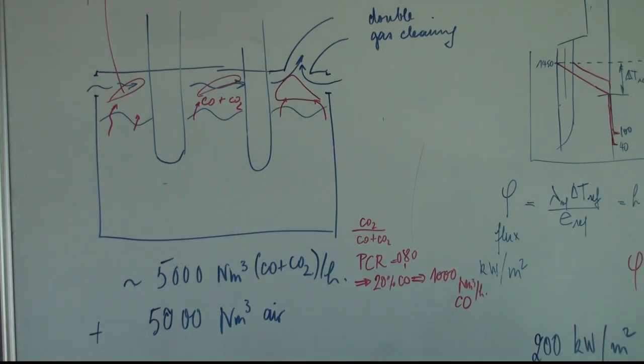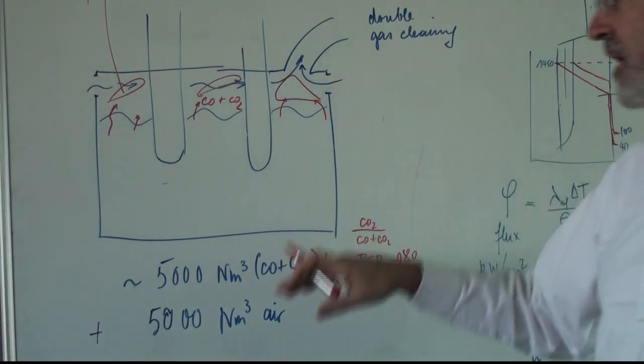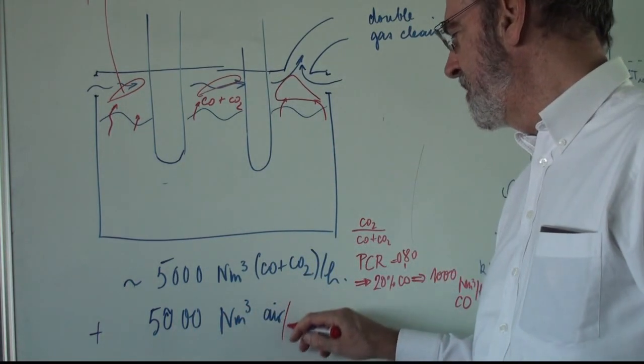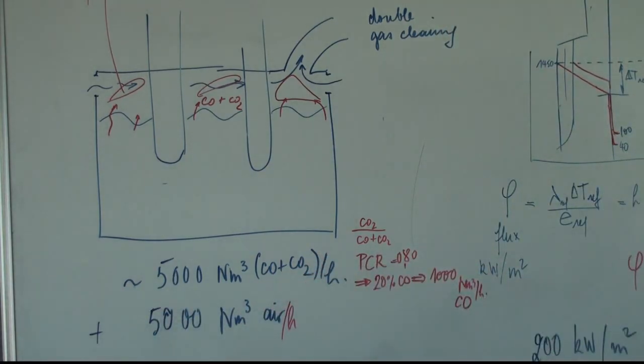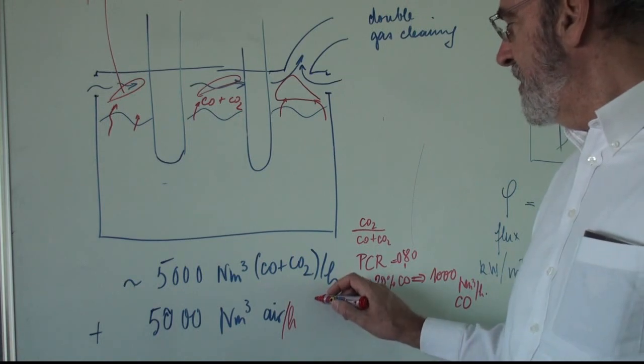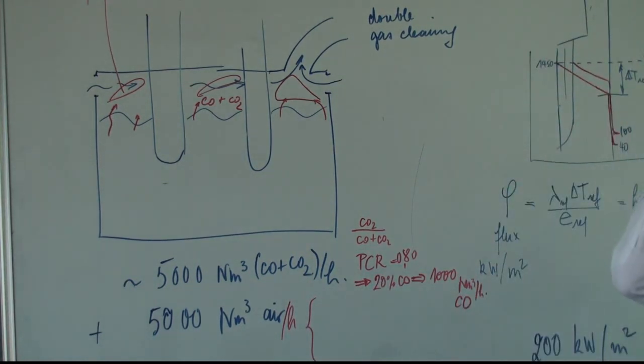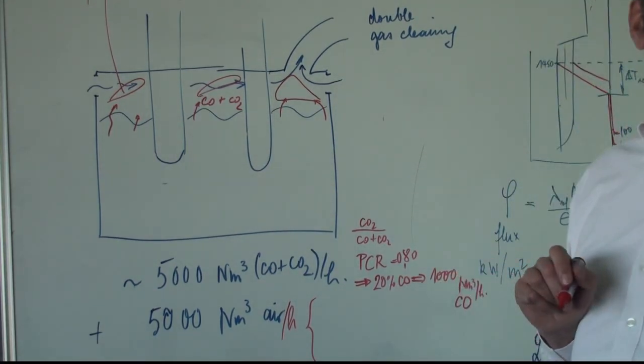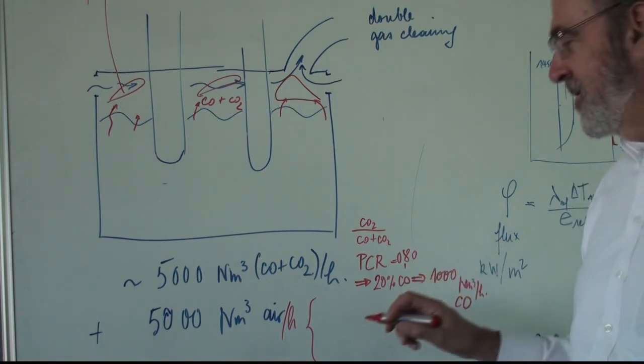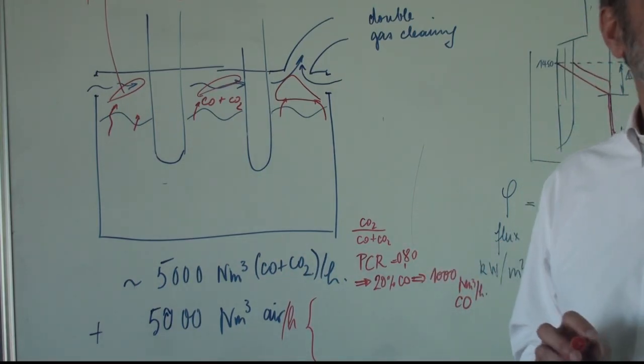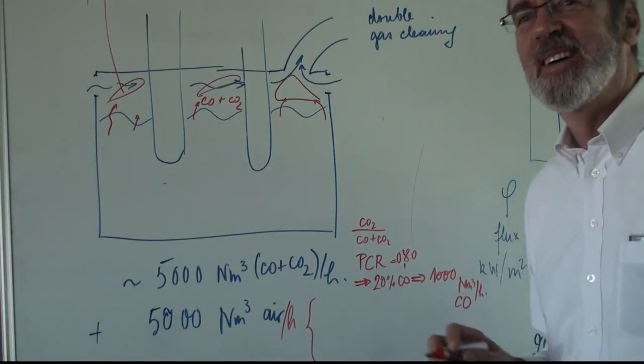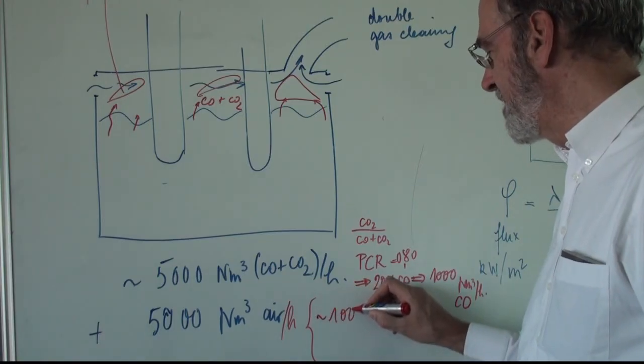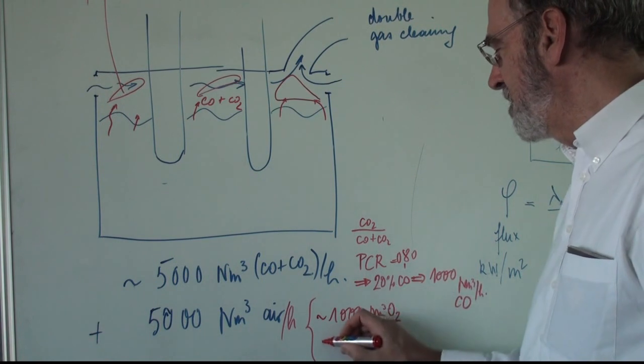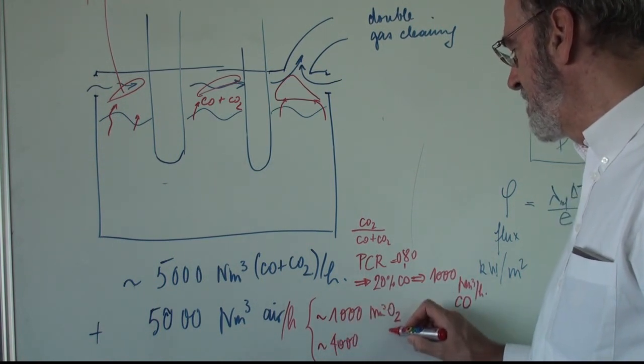You agree? And now, with these openings, I have 5,000 cubic meter air per hour. And this is not much, because you may have 10,000, but if you have only 5,000, it is enough. Because how much oxygen do I have? 5,000 air gives 20%, how much? 21, something. You agree? Okay, so it's roughly 1,000 O2 and 4,000 nitrogen.